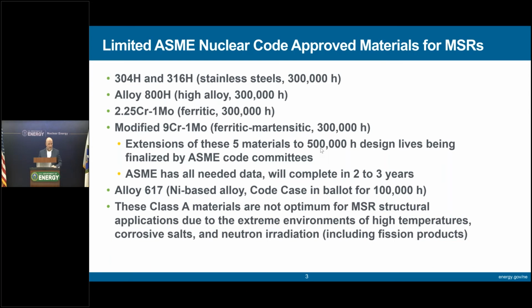On slide 3, limited ASME nuclear code approved materials for MSRs. Obviously, we have 304H and 316H on the list, alloy 800H, 2 1/4 chrome 1 moly, and a modified 9 chrome 1 moly. These 5 materials have been extended to 500,000 design life, being finalized by the ASME code committees. ASME has all needed data and will complete these reviews in the next 2 to 3 years.